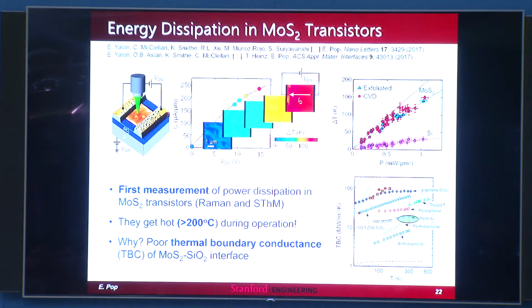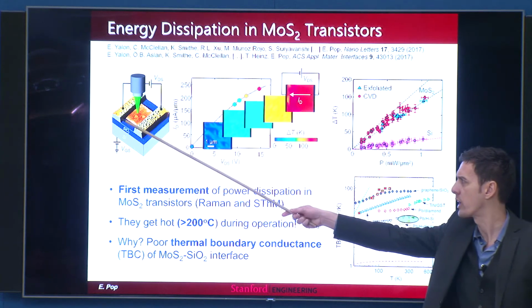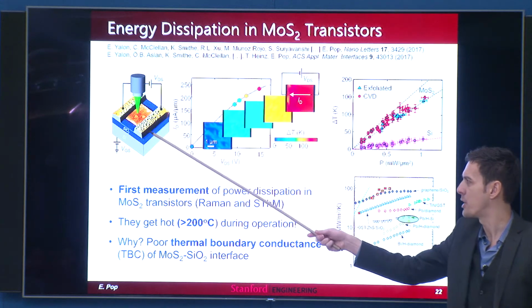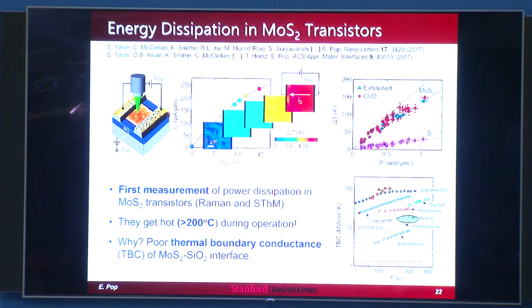One maybe other take-home message from this work is that when you do these IV measurements, especially if you push these devices to reasonably high fields, these are large devices, by the way. You can sort of see this is an AFM image, but this is probably a 5-micron device. So we're taking it to obviously pretty high voltage and high fields. But anyway, when you take these IV measurements, we learn that these devices actually get quite hot.